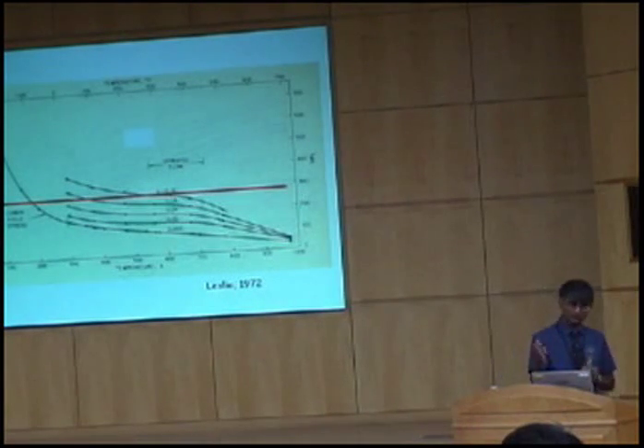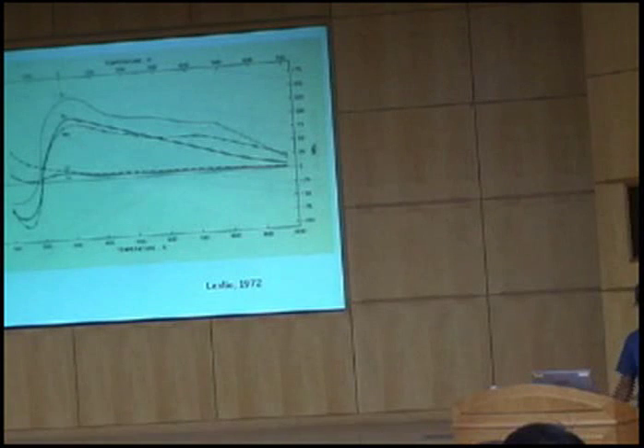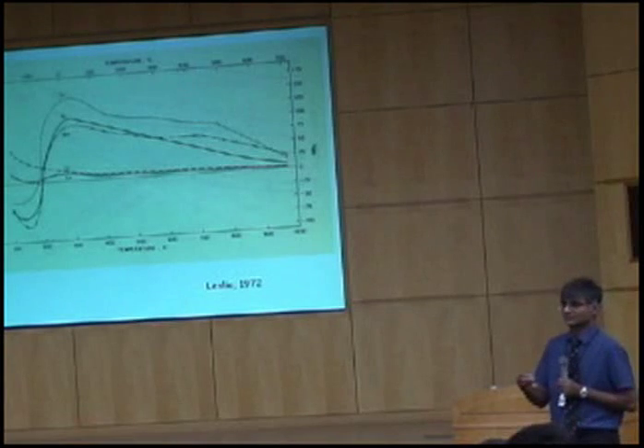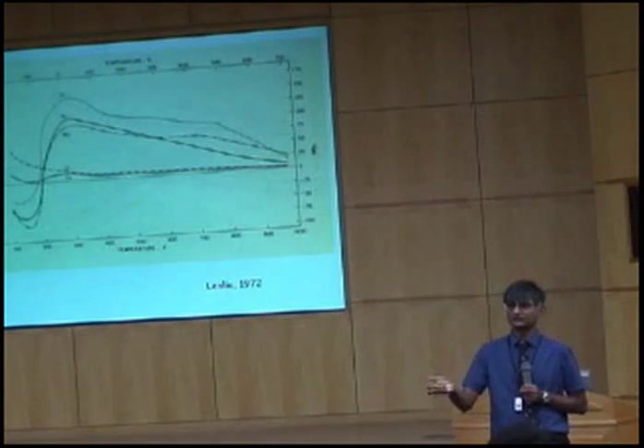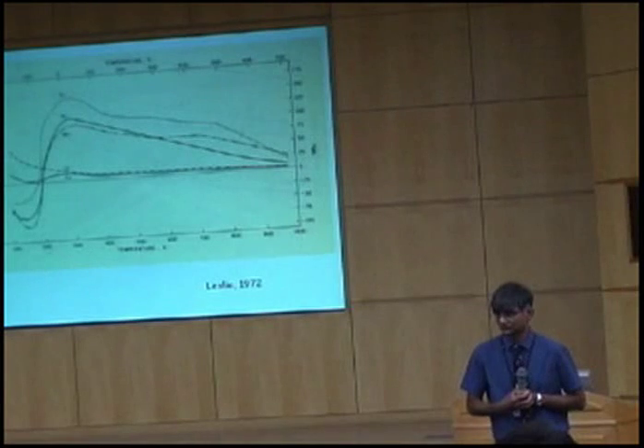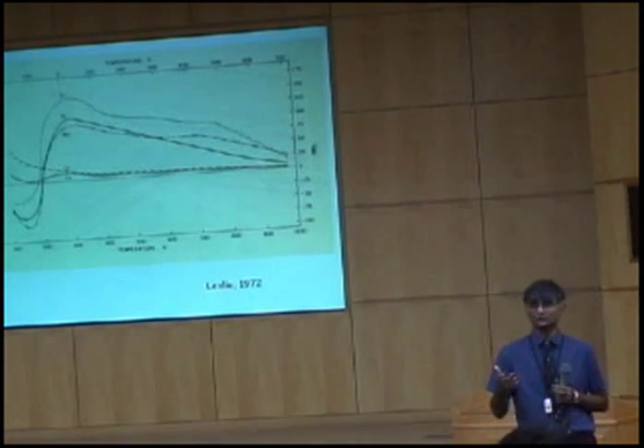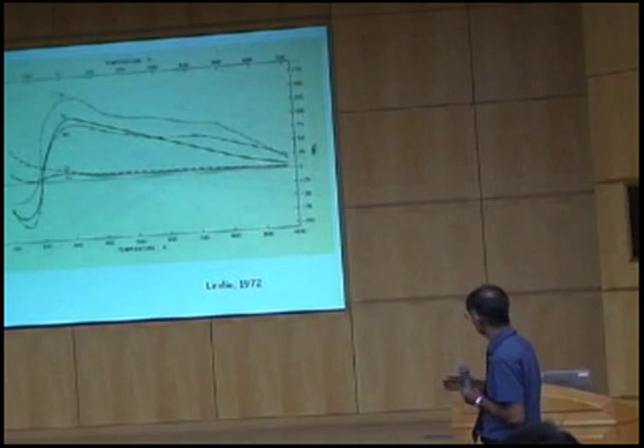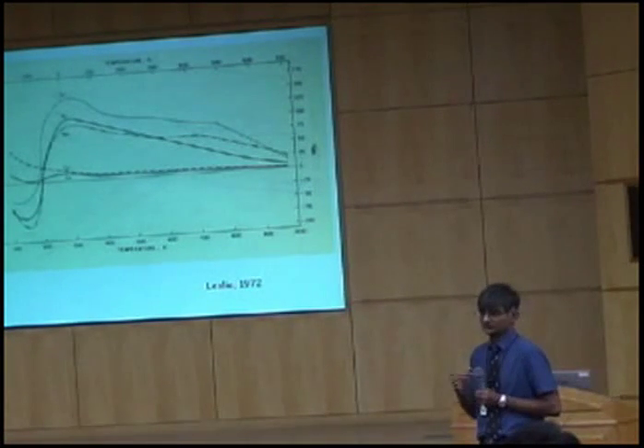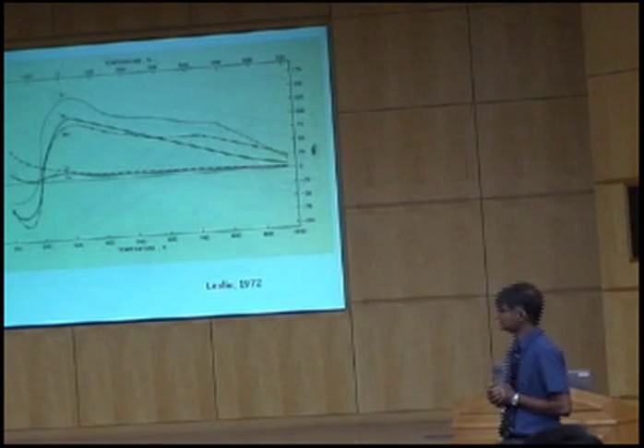So this is a fundamental feature of body-centered cubic iron, that below a certain temperature it prefers to fracture by cleavage rather than by plasticity. And of course what we want is plasticity in order to absorb energy during fracture. Many models of strengthening assume that solid solution strengthening is a constant term per unit of concentration, so for example 40 megapascals per weight percent. But this is quite old work, which clearly shows that solid solution strengthening depends on temperature.